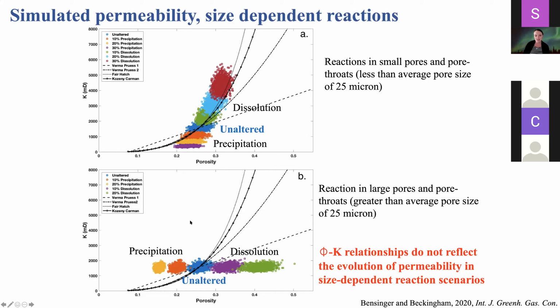If we look at the opposite scenario, so where reactions are occurring in the largest pores and pore throats, so those larger than the average size of 25 microns, you can see dissolution results in increases in porosity with little change in permeability, and precipitation results in decreases in porosity with little changes in permeability. And this is not captured at all by these macroscopic porosity permeability equations.